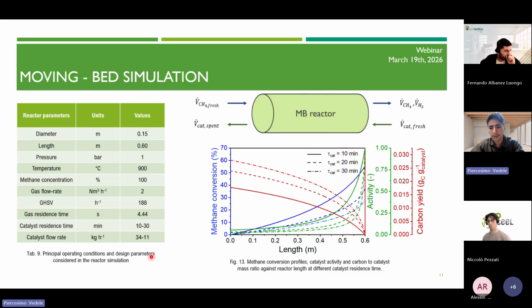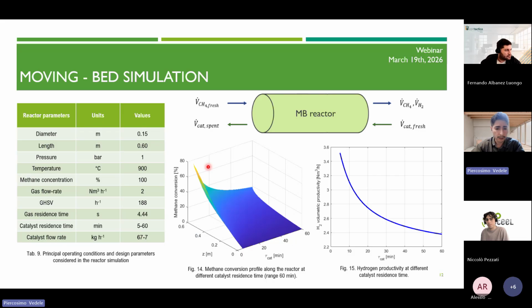Here only to show a sensitivity study where you can see that by changing the residence time of a catalyst inside our reactor, we were able to reach different kinds of conversion. Of course, by increasing the catalyst residence time, we are reducing the methane conversion, because the catalyst is characterized by lower activities, but at the same time we are also increasing the amount of carbon deposited on the catalyst itself.